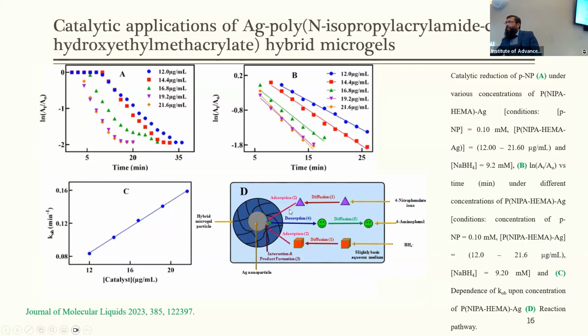This is the actual pathway for catalytic reduction of 4-nitrophenol on the surface of silver nanoparticles. The reactant molecules diffuse from the bulk region to the surface region, then adsorb on the surface of the metal nanoparticle. Then they interact with each other and are converted into product. The desorption of the product takes place and the product molecules diffuse out from the interior region to the bulk region of the liquid. In this way, we were able to successfully reduce 4-nitrophenol into 4-aminophenol, which is a useful green product.